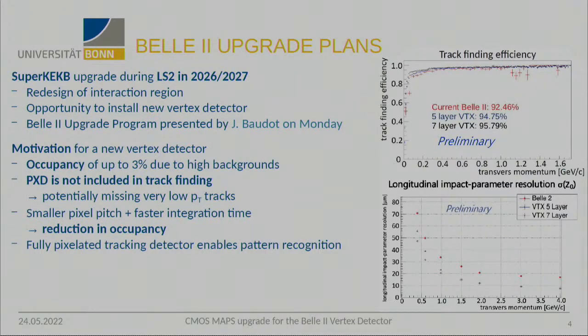So we gain very much in the low PT region, and also with a smaller pixel pitch and a faster integration time, we can significantly reduce the occupancy in the innermost layers, and we want to use a fully pixelated detector to enable fast pattern recognition.